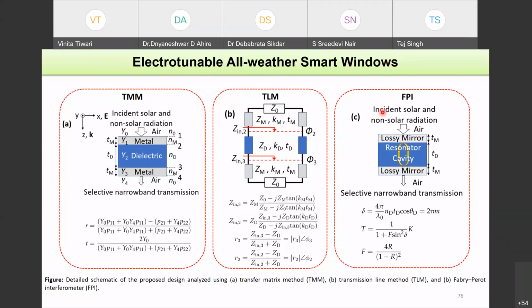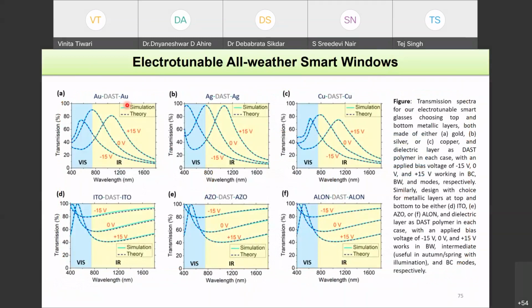You can also utilize Fabry-Perot interferometer conditions and find out the resonance wavelength that each of these metal dielectric metal structures will suffer. These are Au, DAST, Au. This is Ag, DAST, Ag. DAST is the electro-optic polymer. So I am showing here the results for gold, electro-optic polymer, gold, then silver, electro-optic polymer, silver. This one is for copper, electro-optic polymer, copper.